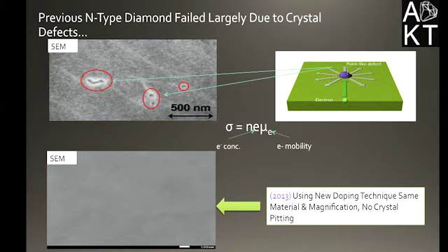And in previous demonstrations of N-type doping, we saw that incorporating these foreign atoms inside of the diamond structure, something very problematic happened. We have crystallographic dislocation. And if we think about this analogously to driving a car down a road, we think about this as like a pothole, because as we know, the conductivity is the product of not only the electron concentration, but also how fast these carriers can move within the material.